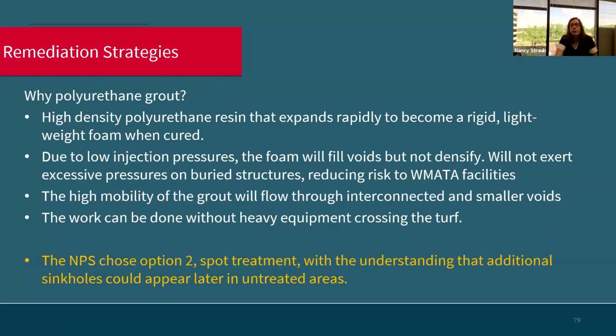One of the things you may wonder is, why did we look at polyurethane grout? Because this project was going to be done immediately next to the metro station, and we were not going to have any way to control where the grout was going, we wanted to make sure that the grout we were using would not put excessive pressure on the WMATA facilities underground. We also wanted to make sure that the grout would expand quickly, be rigid and lightweight, so we wouldn't have problems with later settlement or breakdown. We did not know how interconnected the voids were underground, so we wanted to make sure that the grout was highly mobile, so it could flow through all different size voids.